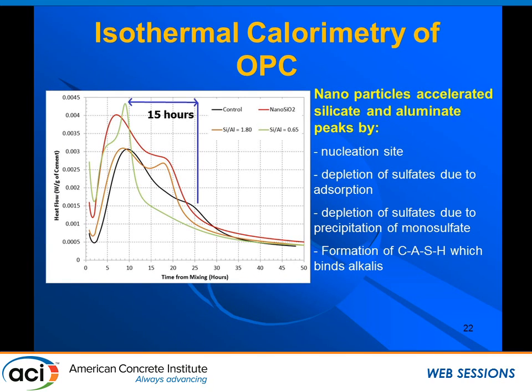When we add other nanoparticles with different silica to alumina ratios, in this case 1.8 and 0.65—0.65 being pretty close to the previous slides' 0.64—in this case 0.65 accelerates the peak by 15 hours. Why? Because on top of what we had before, we have depletion of sulfates with the precipitation of monosulfate. And in this case, instead of only precipitation or formation of CSH, we have formation of CASH.